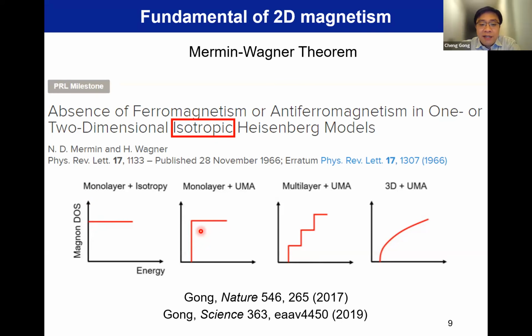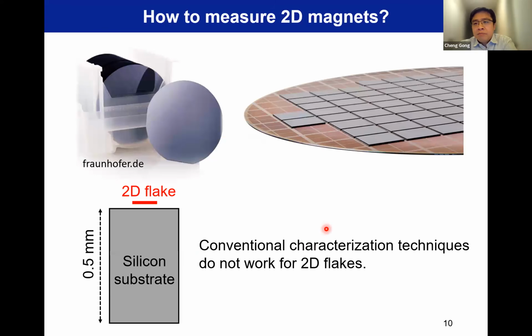And when you have some layers, you will have such a step function, but still there is an onset of a lot of density of states with a gap. The gap here is the key that can sustain your material's long-range magnetic order against finite temperature thermal agitation. So this CGT has the easy axis anisotropy, so it's good. We probably can have the long-range magnetic order.